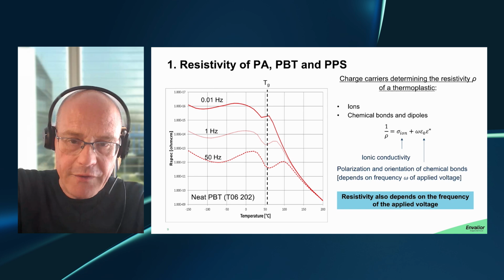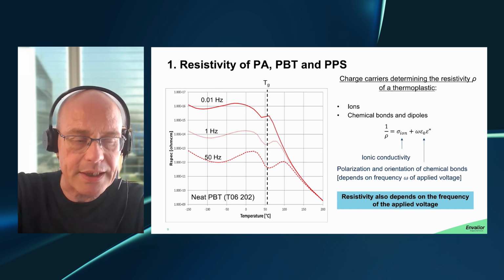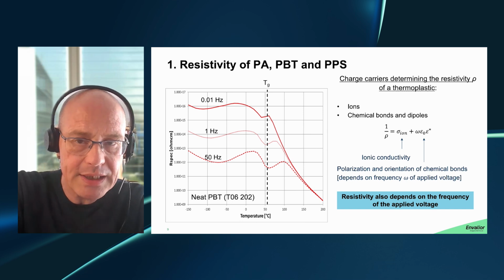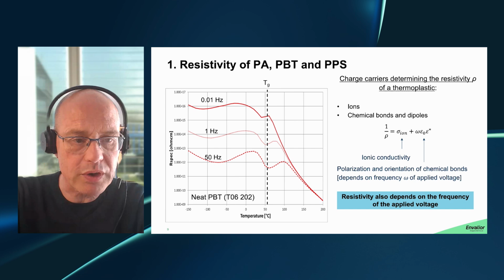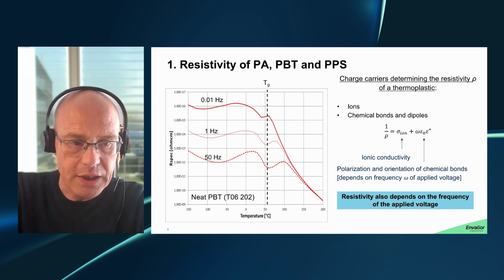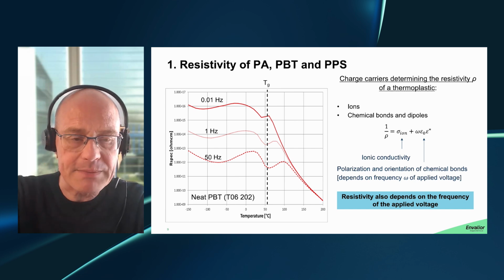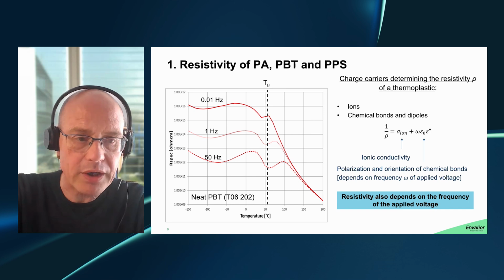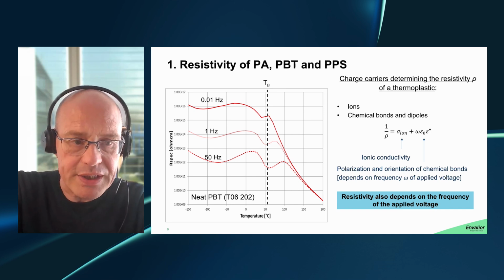If you apply a voltage, basically these bonds get polarized and they orient. And if you apply a voltage of a higher frequency, they get polarized more often per second. So effectively, these bonds then carry more current, and therefore the resistivity of the material tends to be lower.